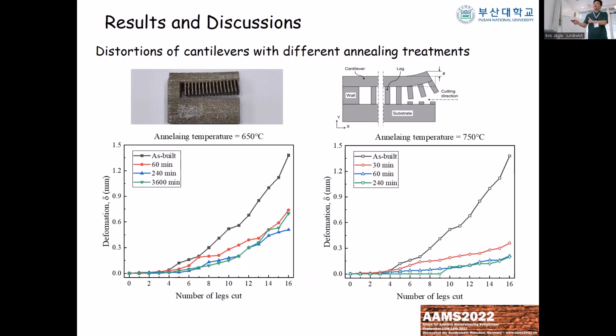And with increasing heat treatment time, as expected, the distortion is decreasing because of the annealing effect. And when we increase the annealing temperature to 750 degrees C, the annealing effect is more pronounced. That is also as expected. But one interesting point here, as a material scientist, is that we cannot completely eliminate the residual stress at this temperature. When we look at the microstructure, at this temperature for this material we are basically doing some dislocation climbing only, so rearrangement of the dislocations, so we cannot completely remove the residual stress, although here we have some diffusion.